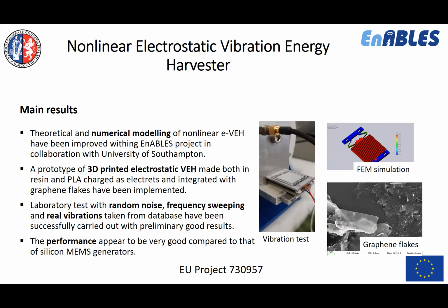So it was not done only in Perugia, but also in collaboration with the University of Southampton. Based on this modelization, some prototype, so based on 3D printing, has been done. So they were made both of resin and PLA. PLA stands for polylactic acid, which is a thermoplastic polymer, charged and can be used as electrets, and integrated also with some graphene flakes. And all these materials have been implemented to manufacture some 3D printed energy harvester.